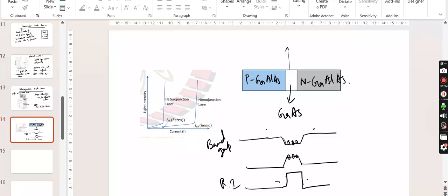So confining both current and light within the lasing volume ensures that the minority charge carriers recombine here and emit light. This results in a significant improvement in the performance of the laser by establishing increased electro-optic efficiency and reduced heat dissipation. It is not surprising that room temperature CW operation is readily achievable from a double heterojunction laser.